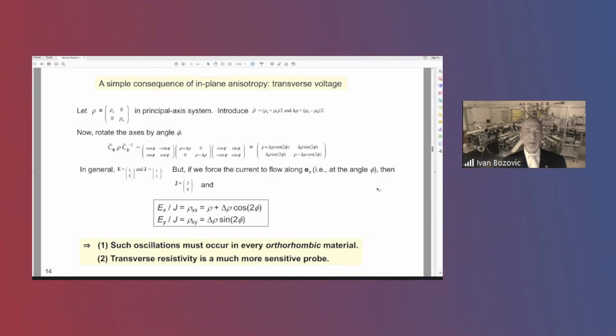So here is a little theoretical background. Imagine that you have a material which is tetragonal, then its resistivity tensor can be drawn as a matrix, and this matrix must be diagonal because every direction is an eigenvector for the current because of the rotational symmetry. And then this matrix will stay diagonal no matter how you rotate the axis. On the other hand, if the crystal is orthorhombic, then this matrix is only diagonal in the so-called principal axis coordinate system. If you rotate the current direction azimuthally, then the current vector is not an eigenvector anymore, and that means that the off-diagonal matrix element must be non-zero.